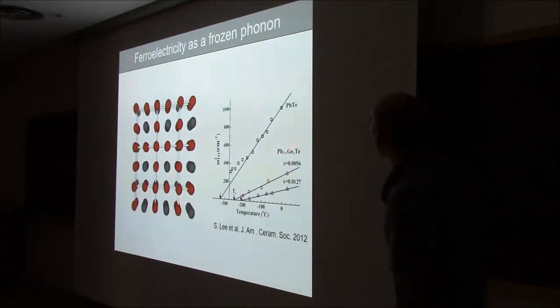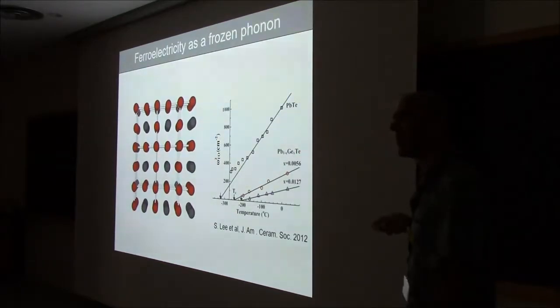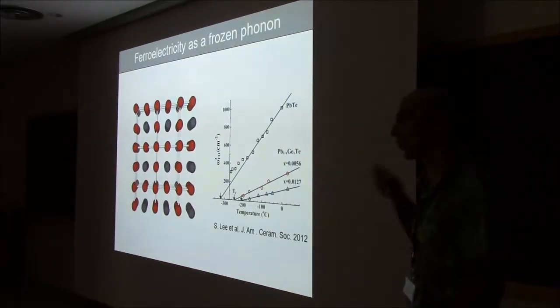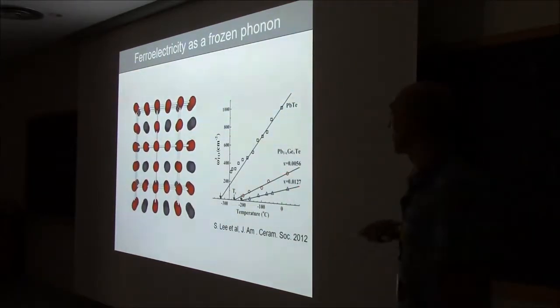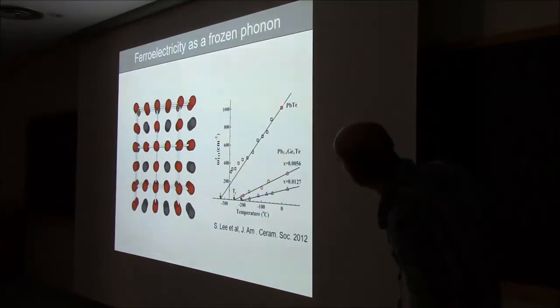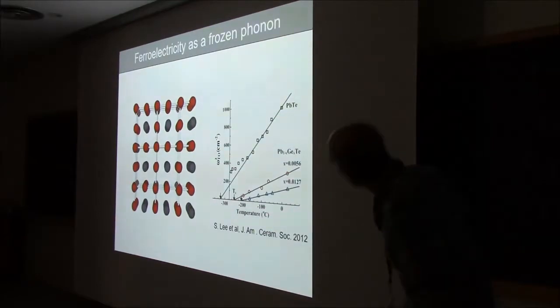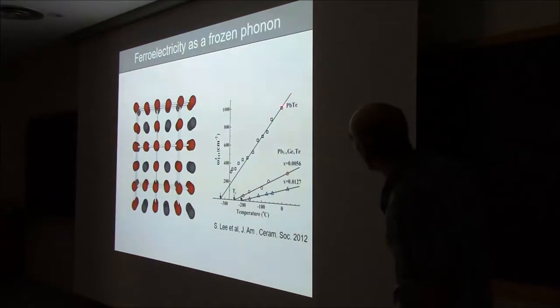Okay, this example, in fact, is good because this is not an oxide. It's lead telluride and lead germanium telluride. These are half metals or semi-metals. These are basically very conducting. If you wanted to measure a hysteresis loop on this, it would be difficult. However, if you look at the phonon spectrum, you see that, okay, this phonon never freezes. It is the frequency of the phonon as a function of temperature. This transverse optical polar phonon, for this composition, never freezes, so this is never going to be polar.